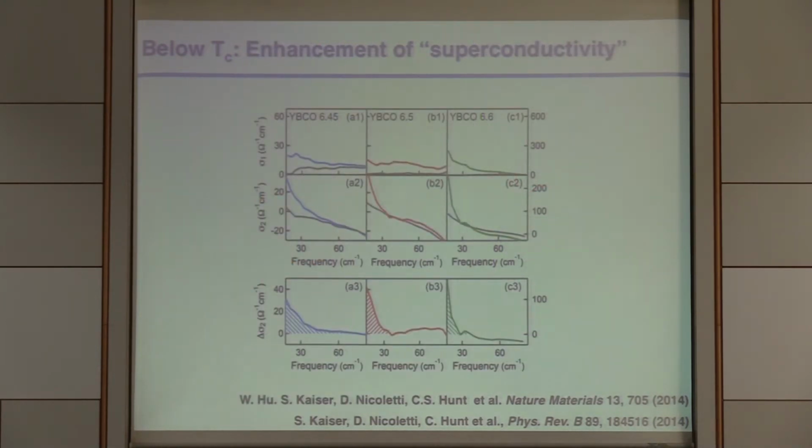because the superfluid density is getting larger. And you can see this even more clearly if you plot the imaginary part of the optical conductivity, which tells you about the superfluid density in one particular direction, which in a good superconductor is supposed to scale with a 1 over omega dependence, so diverging as the frequency gets smaller. And what you can see is that if you start in the gray state, which is already a well-recognized superconductor, because this is apparently a very clear 1 over omega response, and you pump the system, what you can find is a much stronger 1 over omega response in the driven state. Again, indicative of the fact that your superfluid density is getting stronger.